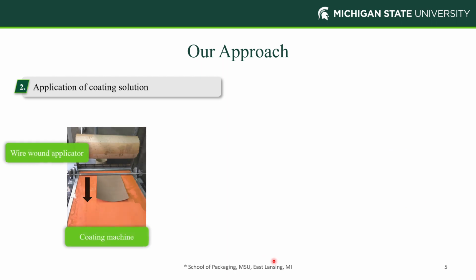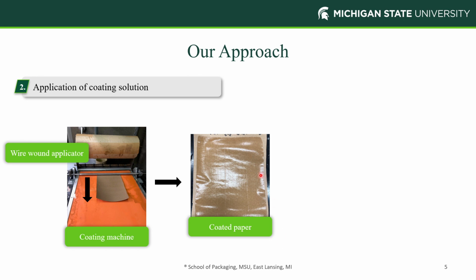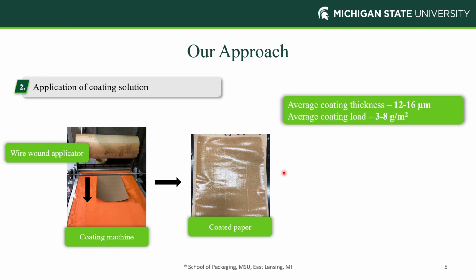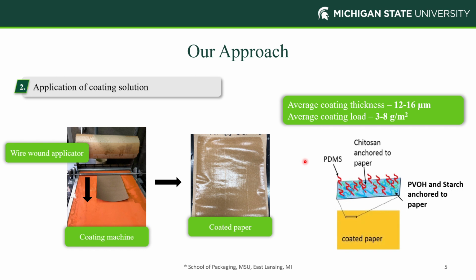This solution is further applied onto the paper using a coating machine, and we get a really smooth film on the coated paper, like you can see in this image here. And this film would be about 15 microns thick, depending on the concentration and the ratio of starch and polyvinyl alcohol. And according to our hypothesis, the PVOH, starch, and the chitosan should be anchored onto the paper and cover the pores of the paper, like you can see in this image here of the coated paper with the smooth even film that covers the pores.